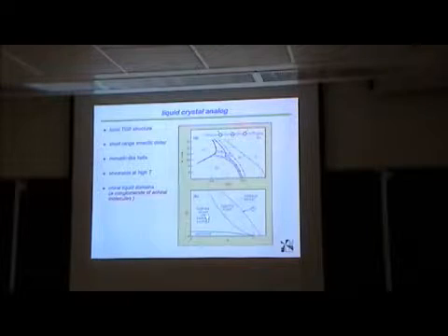So here in the liquid crystal case, this is just changing the chain length in the tail of this molecule versus temperature. The Smectic A phase is analogous to the Meissner phase. The TGB phases are analogous to the vortex glass. There's a nematic phase, which is analogous to the vortex liquid. The isotropic phase is analogous to the normal metal.